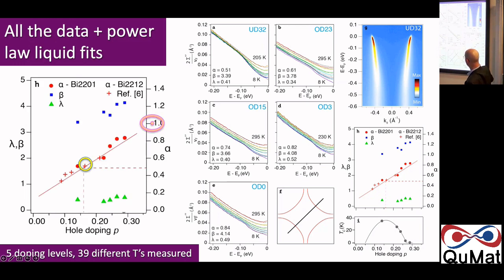So I show that a bit bigger on this side. So at optimal doping, it really is linear. So the transport is showing us a linear behavior versus temperature, and the photoemission is showing us a linear behavior versus temperature and frequency. And if we wanted to get to 1 for alpha, which would be the Fermi liquid, we'd have to go up to a doping level which chemically cannot even be made with these crystals. Right? So our sample, which is outside the superconducting dome, still has an alpha of about 0.8. So that would mean it's omega to the 1.6, T to the 1.6. Still not a Fermi liquid, even though it's non-superconducting.